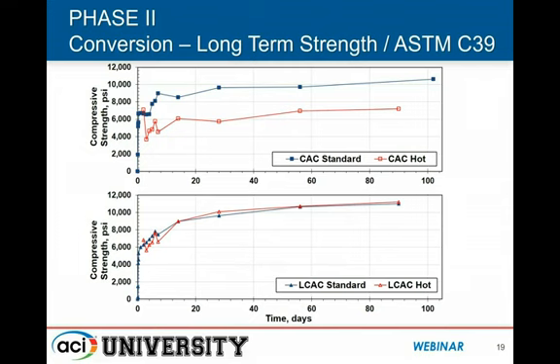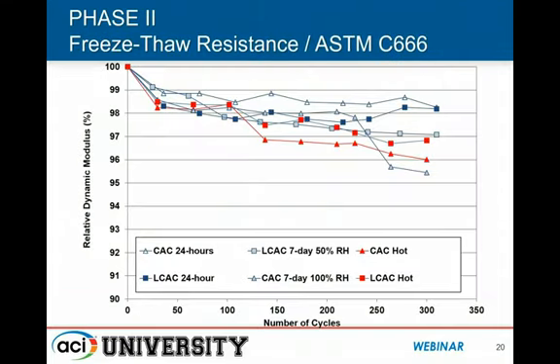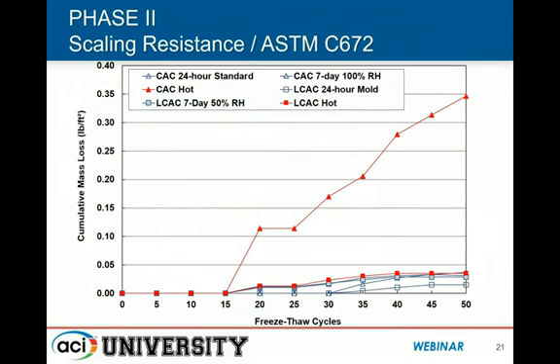What happened, though, is when we started to add the latex, we began to discover that it gave us great freeze-thaw durability. As you can see here, we had well over 300 cycles, and the relative dynamic modulus that we were seeing in the sample significantly outperformed some of the other materials that we had previously investigated. But we began to see that there was some scaling resistance issue with the material when it was not utilized with the latex. So this is where the latex came in as a significant improvement from the durability side.